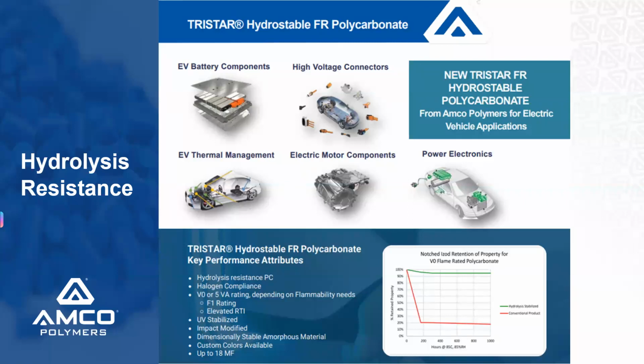So we developed version 1.0, where we were able to pass their test, where they took the parts for 2 weeks, put them under 85 degrees C, 85% relative humidity, and then tested several of the material properties after that, and determined with our version 1.0, we didn't see any degradation of properties. Since then, Tom has formulated what I call version 2.0, and we're currently testing it up to 3,000 hours, and right now we're not seeing any degradation of the properties. Again, when conditioned to 85% relative humidity and 85 degrees Celsius in temperature.